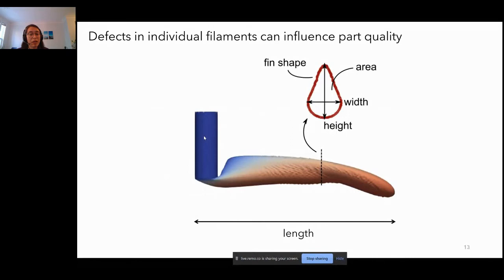So this is a simulated filament. You can see that blue column is the ink that's inside of the nozzle, and you have a filament that's coming out of the nozzle. If you look at the cross section of that filament, it's not circular like the nozzle is. It actually has a sort of fin shape, so it narrows towards the top and towards a point. So I'm going to express that cross section in terms of the aspect ratio, the height over width.